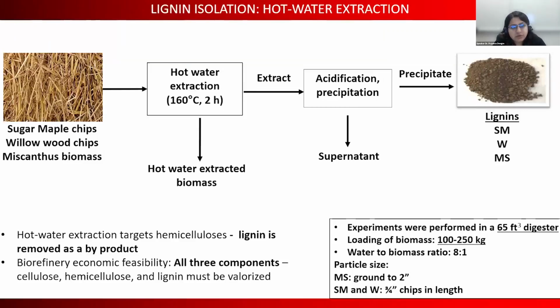The lignin that was produced was from three species: sugar maple, willow, and miscanthus. This is what I will be talking about. We did extract lignin from other species as well. The biomass undergoes a hot water extraction at 160 degrees for 2 hours. The extract is then acidified to pH 2, and the lignin is precipitated. The precipitate is then freeze-dried or oven-dried and collected, which is then used to make the resins.